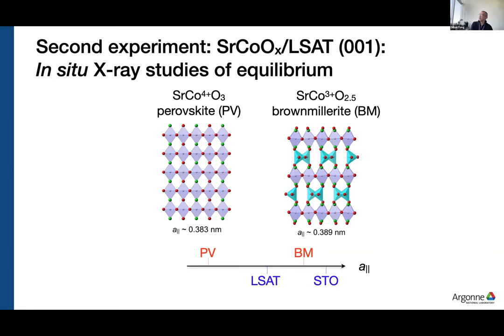The other good description is shown by this work on, again, strontium cobalt oxide on LSAT. And here, I'll just describe some of the experiments we conducted for strontium cobalt oxide in equilibrium. So when you grow strontium cobalt oxide on strontium titanate, like I already discussed, it really favors the Brownmillerite phase, okay? I'm showing the lattice parameter at the bottom. And so the perovskite phase is on the left. The Brownmillerite phase is on the right. You see the Brownmillerite is pretty close to the STO lattice parameter.